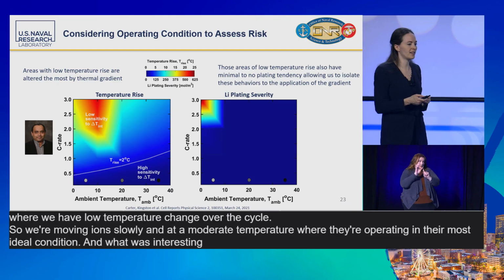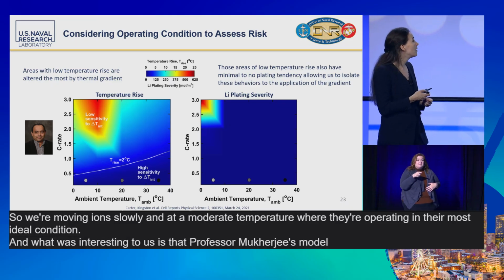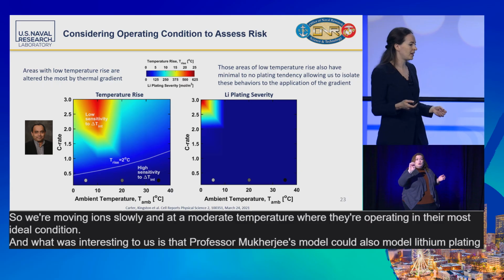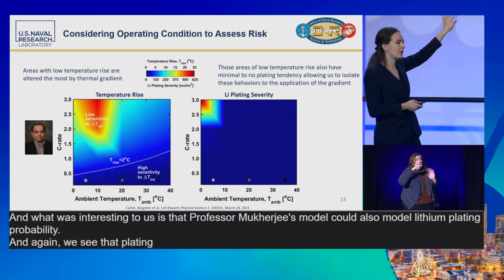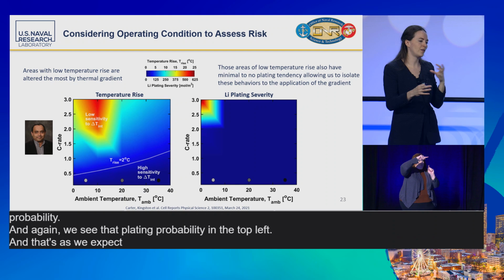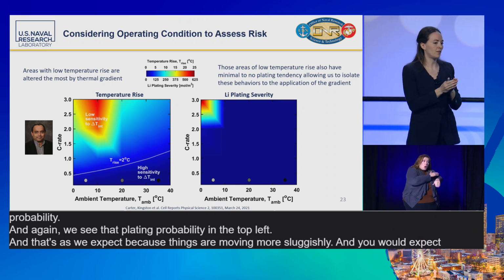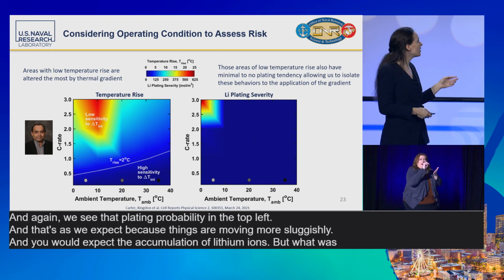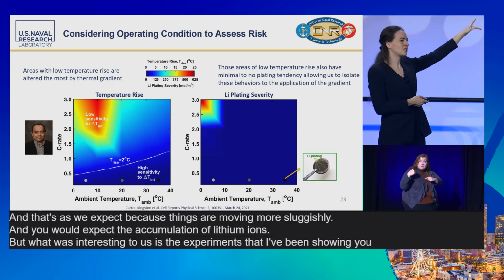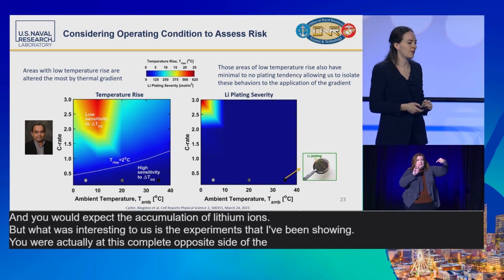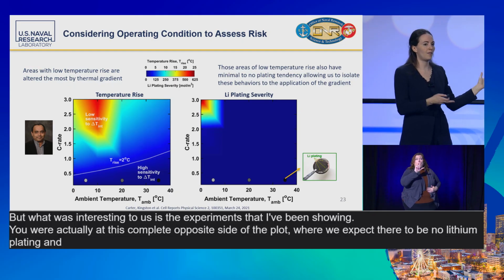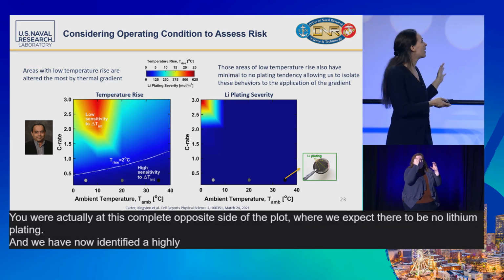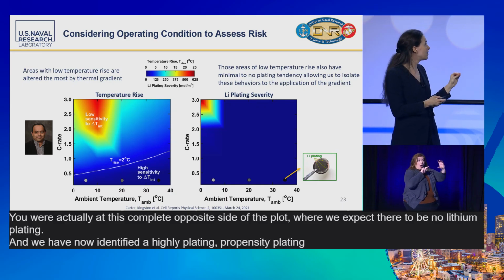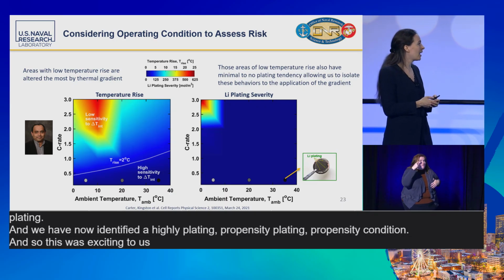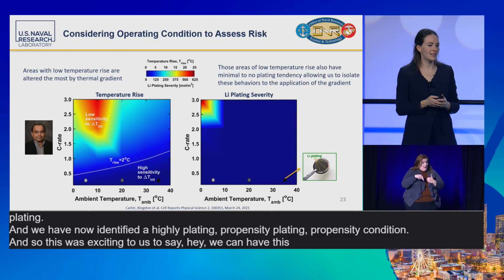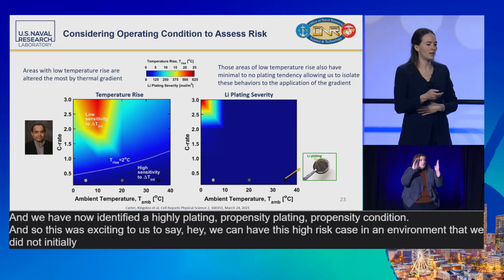And what was interesting to us is that Professor Mukherjee's model could also model lithium plating probability. And again, we see that plating probability in the top left. And that's as we expect, because things are moving more sluggishly, and you would expect the accumulation of lithium ions. But what was interesting to us is the experiments that I've been showing you were actually at this complete opposite side of the plot, where we expect there to be no lithium plating, and we have now identified a highly plating-prone condition. And so this was exciting to us to say, hey, we can have this high-risk case in an environment that we did not initially think that we could.